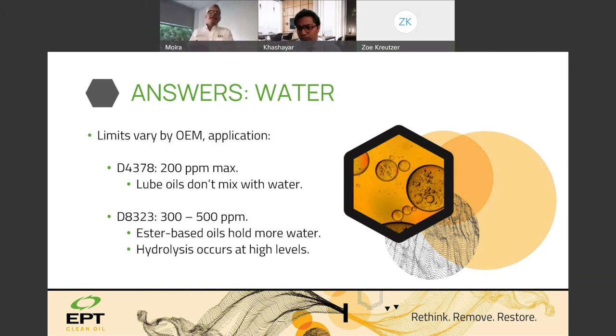and could be ripped out with an oil coalescing system quite easily. The problem is, if you get a lot of oxidation material in that oil, the polarity of these mixtures starts to interfere with each other and interfere with water separation. Because water is polar, and because oxidation material is polar, you're going to get a scenario where the water is more attracted to the oxidation material than it is to the oil itself. And in this application, they will not separate anymore. That being said, if you remove the oxidation material, then those two would separate naturally. Okay, so if you have an oil coalescing system that's not working great because of water separation issues, it's because you normally have too much oxidation material in your oil. There can be other specialized scenarios in this as well.